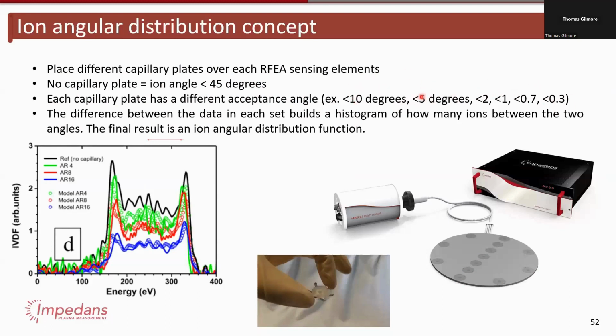So you build up a histogram. And by the end, you can be getting down to very small angles. And then you can get a distribution of where all the ions are at. So the final result here is an ion angular distribution function.